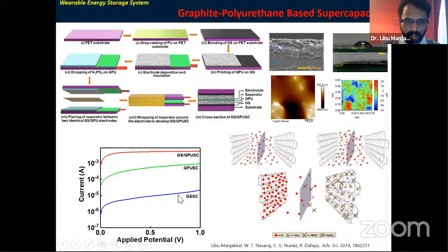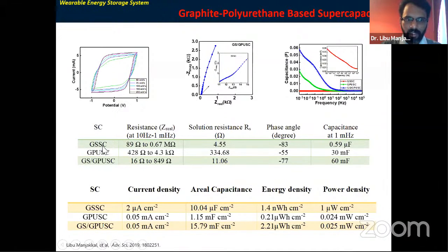And then you can see here, I compared this with different types of supercapacitor, like a graphene sheet one, a graphite polyurethane one, and a layered one also. Depending on the potential, ions from the phosphoric acid distribute around the electrode. Then comparing the different supercapacitors, you can see here GSSC and GPUSC. GPUSC means graphite polyurethane devices, which, compared to GSSC, show a very high capacitance. You can see here pure graphene gives 0.59 microfarad, but with the graphite polyurethane composite, you get a high performance of 30 millifarad.